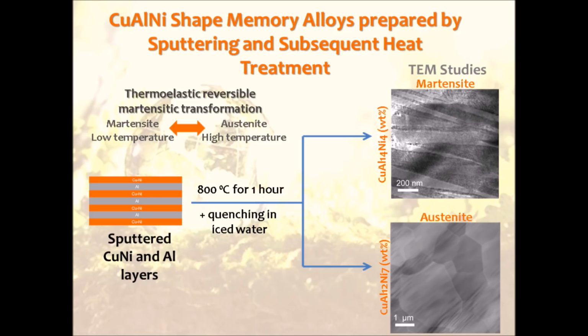Shape memory effect is a thermoelastic reversible martensite transformation between the low-temperature martensite and the high-temperature austenite phases. When it comes to copper aluminum nickel shape memory system prepared by sputtering and heat treatment, the process applied after depositing is quenching in iced water after holding the sample at 800 degrees for 1 hour. The room temperature phase shifts from martensite to austenite due to a gradual change in composition. Quenching as an additional step helps in obtaining shape memory effect. However, is it possible to induce shape memory effect in one step?